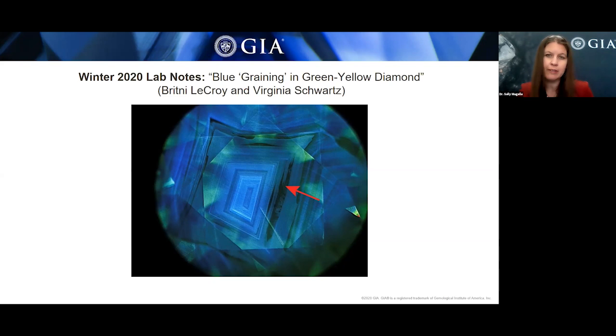Now, in the vast majority of natural diamonds, they have nitrogen-related defects that typically absorb in the blue, thus causing the transmission window due to irradiation to shift to the green. However, in diamonds that have very low to no nitrogen, they can be irradiated to a blue color. Or in the case of this diamond, only those portions that had a very low nitrogen were irradiated to blue, thus causing that blue graining.